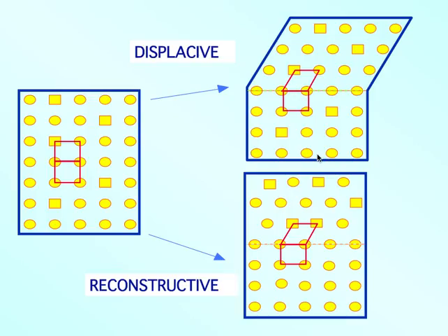This was the basic structure defining the mechanisms. The pattern in which we have the atoms arranged in the austenite can be homogeneously deformed into a different pattern, but then there is the consequence that we get the shape deformation. Whereas reconstructive transformations — if I cut this triangle off and transport it to this side, retaining the external shape — that's the diffusion required to get reconstructive transformation, and in that process you get a rearrangement of atoms.